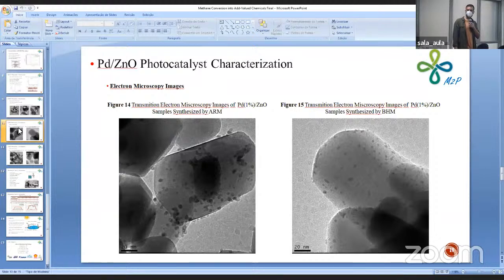In here, we have the palladium-containing samples. Those black dots in here and here are related to the palladium in the samples. At figure 14, we have the alcohol reduction method samples. And at figure 15, the borohydride reduction method samples. And we see a difference in the size of the particles and in the agglomeration of them over the zinc oxide surface.